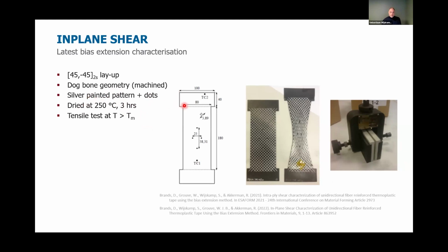Machined a dog bone from the laminates, for a good introduction of the force into the laminate. Using a template to make this crosshatch pattern plus dots, so that you can recognize 4 dots here. Those are used by the extensometer to measure strains in 2 directions, and the crosshatch pattern is to analyze the complete deformation field.